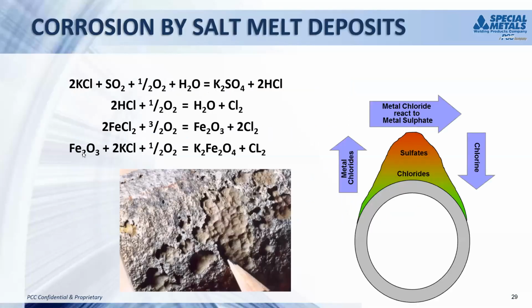Next slide. So this was basically an experiment created at Special Metals with salt and metal chlorides to illustrate how, as these reactions take place in the plant, they concentrate and condense the nasty materials, your chlorides and other halides, into a very aggressive media that's much more concentrated than it would have been in a normal situation. As you can see on that tube sheet, there's some pretty severe corrosion on the edge of that pipe due to the concentration of these melted salt deposits.